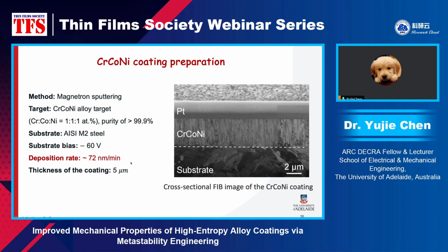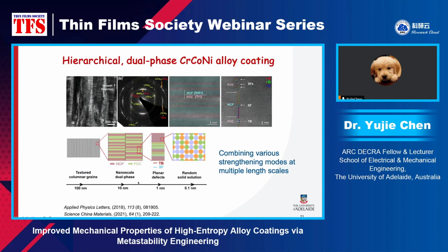And also the deposition rate here is very important because the higher the deposition rate, the higher the possibility that you form planar defects like twin boundary and stacking faults. So here is the structural feature of this coating. We can see they have structural features at multiple length scales, right? Such a hierarchical structure allows for a unique combination of a variety of strengthening mechanisms at multiple length scales. So the combination of these strengthening mechanisms will give us exceptionally high strength and ductility.